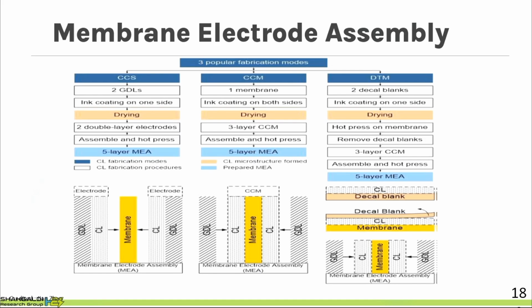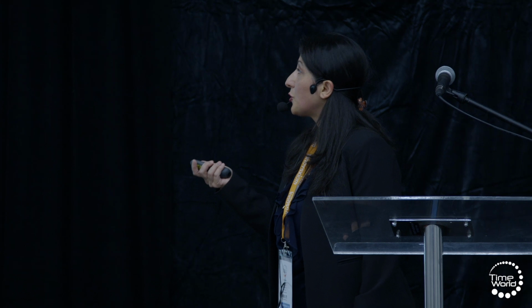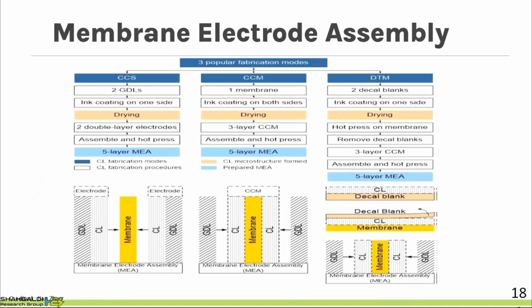And then, okay, so now we talk about the type of material that we have. We talked about, for example, the state-of-the-art catalyst, type of ionomer, membrane. So now, how do we make the MEA? Normally we have three methods for making our MEA. We have catalyst-coated substrate, we have the decal method, and we have the CCM method. So catalyst-coated substrate is when we make the ink and deposit our ink on our GDL directly, so it's easy, without any problem, very easy. However, the majority of our catalyst is going to sink inside the pores. So this method is perfectly fine if you have high loading. If you have high loading of catalyst, then it's easy to produce CCS. But if you want to bring down the loading of catalyst, then we may think about CCM or the decal method.